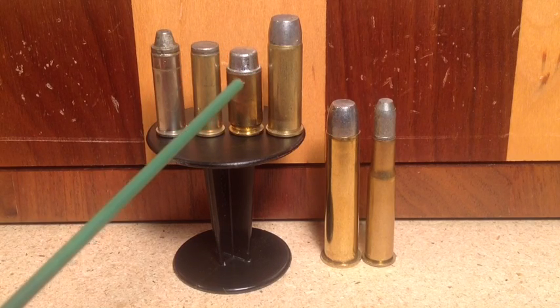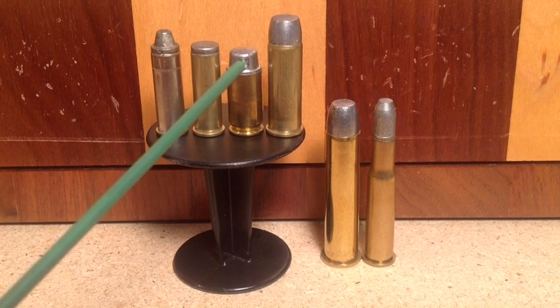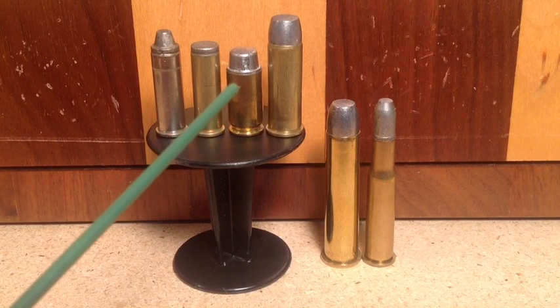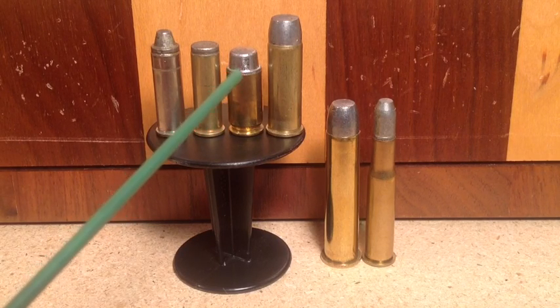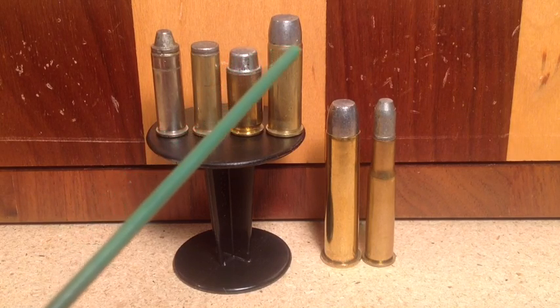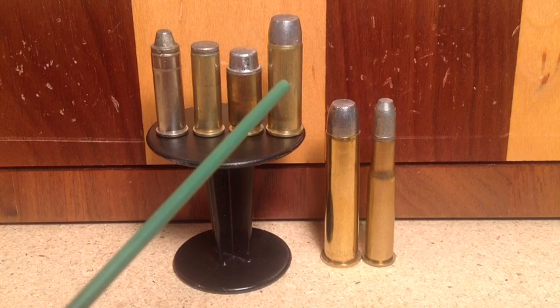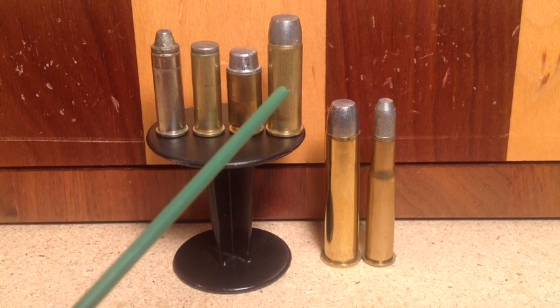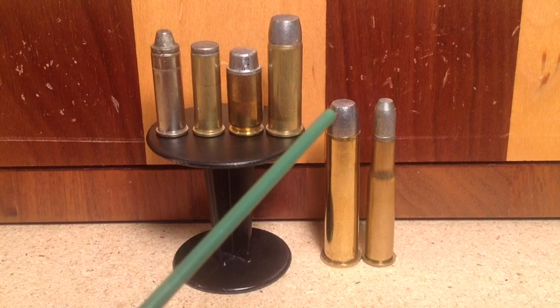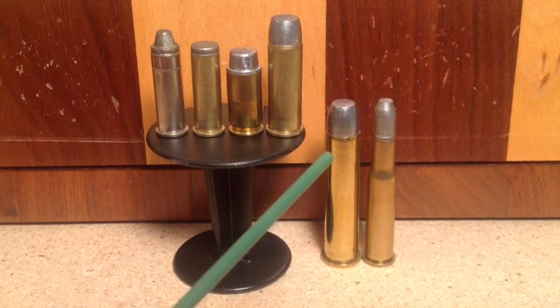If you're shooting plus P or auto pistol rounds — because you need good lead hardness to function hitting the ramp and going into the barrel — you need Brinell hardness number 15 to 16. Plus P will take you up to 950 feet per second. If you're shooting anything above plus P all the way to full magnums, then you need Brinell hardness number 18, which is good all the way up to light rifle velocity — 1700 feet per second or less.